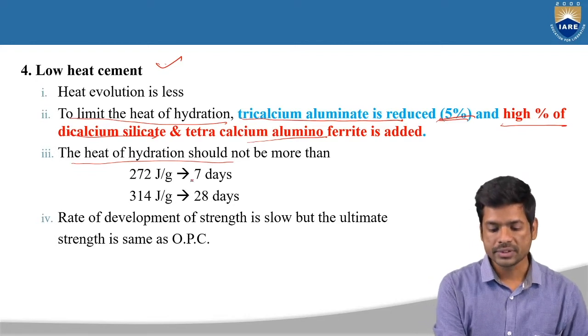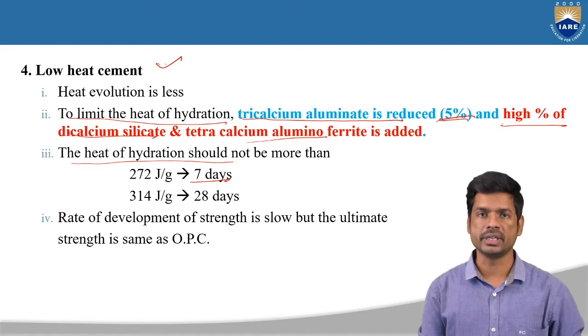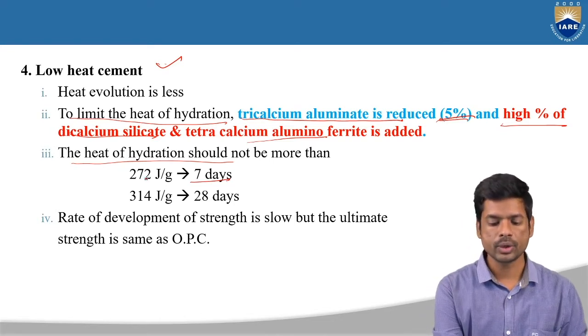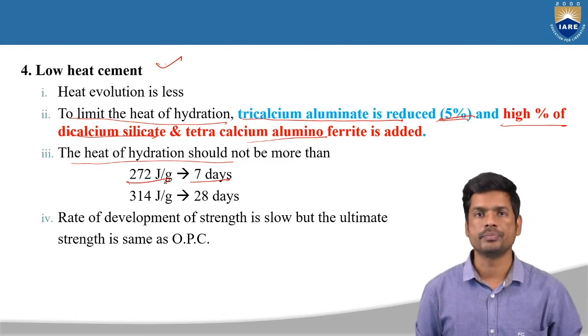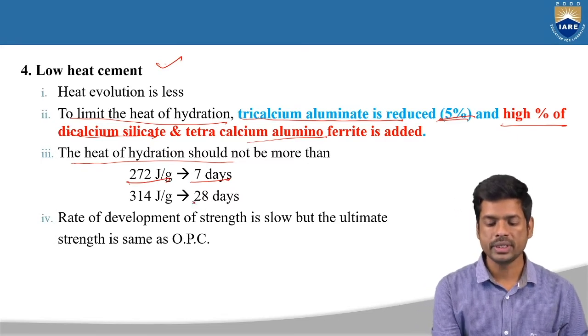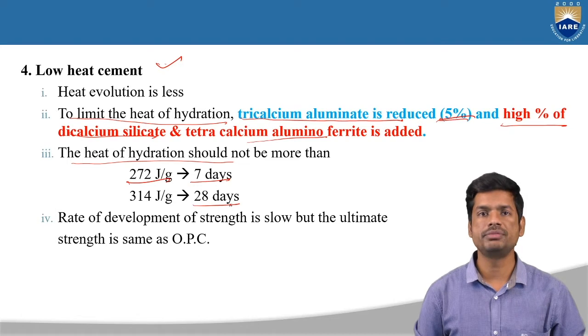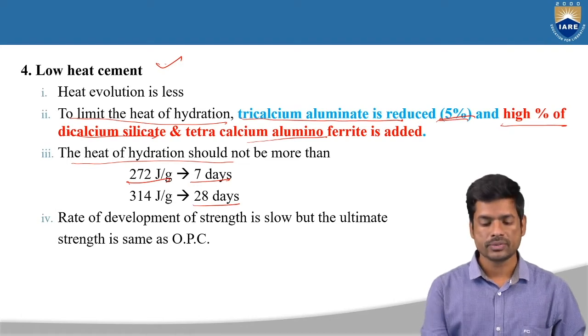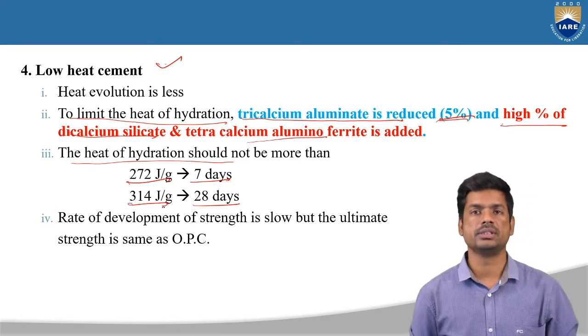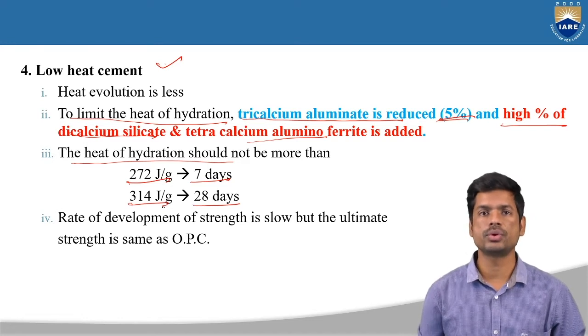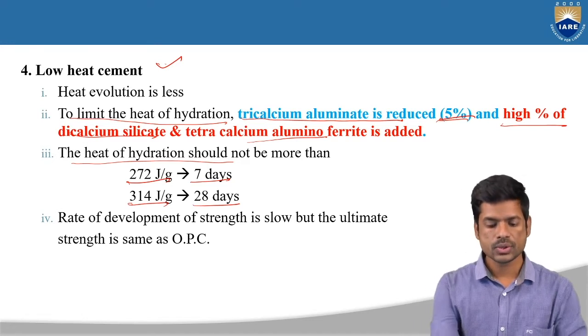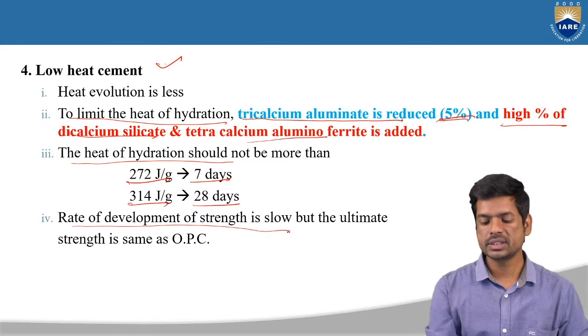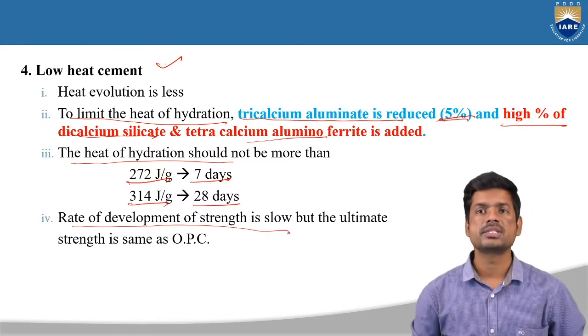So here, after 7 days, if you check the heat evolution from this particular type of cement, that will be around 272 joules per gram. Okay, and next, after 28 days, if you check the heat evolution, then it will be around 314 joules per gram. That means 314 joules per gram. Okay, so rate of development of strength is slow, but the ultimate strength is same as OPC.